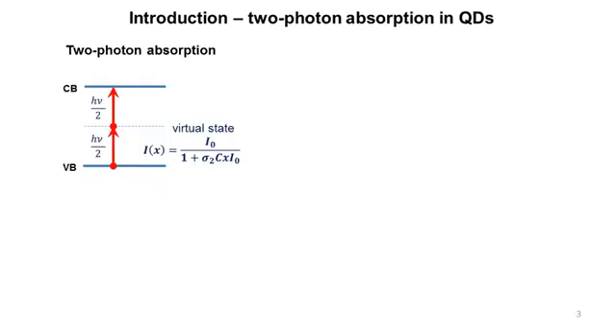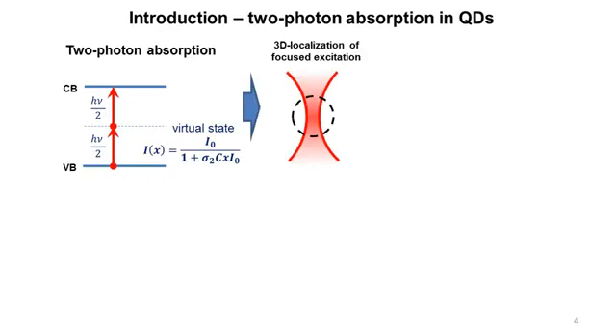One of the most impressive features of quantum dots is their capability for highly efficient two-photon absorption. Two-photon absorption makes it possible to utilize the energy of photons, the energy of which is less than the band gap. Moreover, this process is non-linear in intensity, which determines some of its features, namely the need to use a high excitation intensity and the possibility of three-dimensional localization of excitation by excitation focusing.